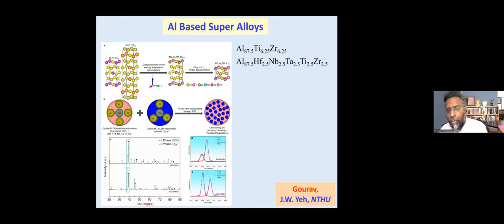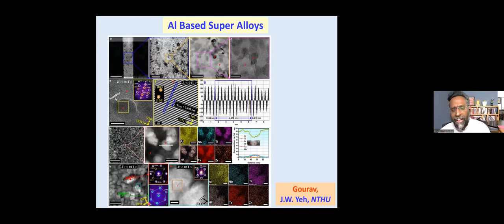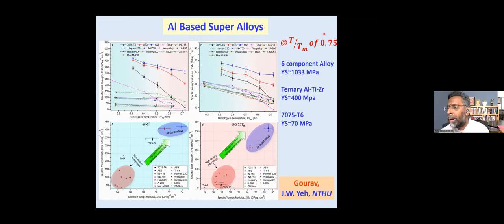Now what we did was we made these alloys, the so-called multi-component alloys containing aluminum, and developed exceedingly fine nanoparticles of a gamma prime kind of structure in a gamma matrix. And what we achieved with that is, at 0.75 of the melting point, okay, which means we are close to the melting point of the alloy.